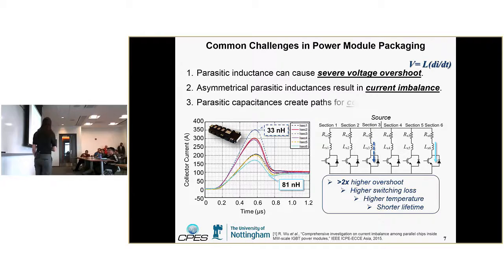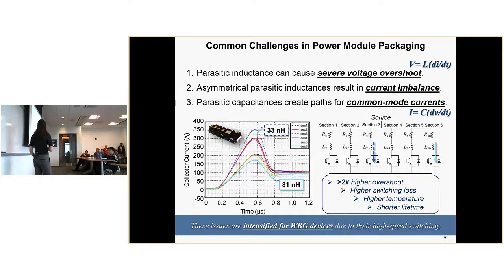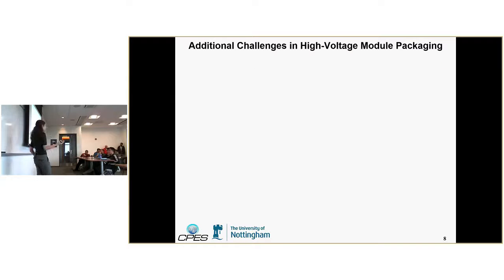A further issue is the parasitic capacitance. Across that insulating substrate, there's an inherent capacitance. And so under high dV/dt transients, you can get common mode currents flowing through your system ground, which is also significant. Of course, these are all intensified for wide bandgap devices because of the high-speed switching, the higher dI/dt and dV/dt. In addition to that, you have further challenges when it comes to high voltage packaging.